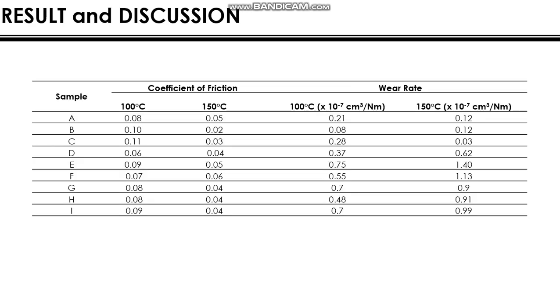Result and discussion. The lowest coefficient of friction at 100 degrees Celsius is in sample D, and the highest coefficient of friction at 100 degrees Celsius is in sample C. The lowest coefficient of friction at 150 degrees Celsius is in sample B, and the highest coefficient of friction at 150 degrees Celsius is in sample F. The lowest wear rate at 100 degrees Celsius is in sample B, and the highest wear rate at 100 degrees Celsius is in sample E. The lowest wear rate at 150 degrees Celsius is in sample C, and the highest wear rate at 150 degrees Celsius is in sample E.